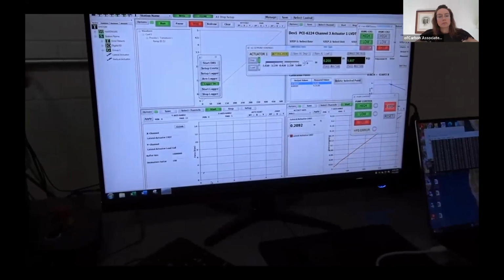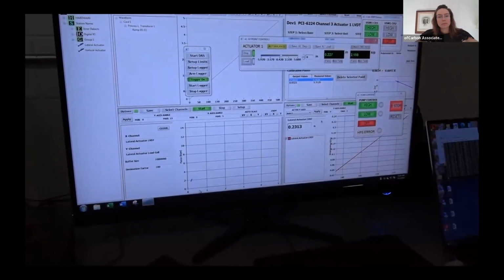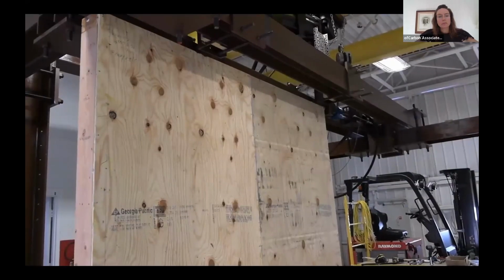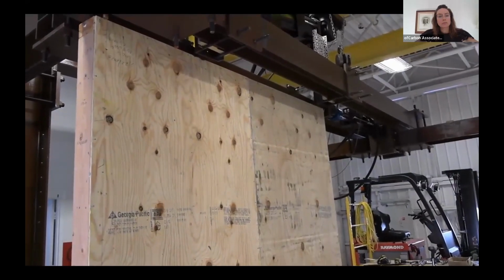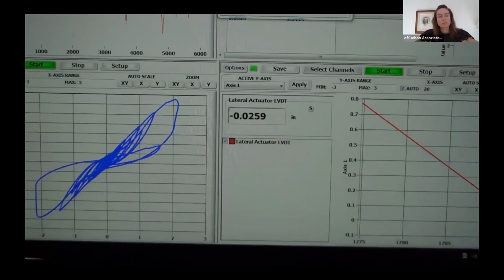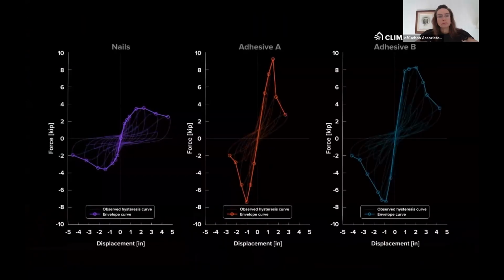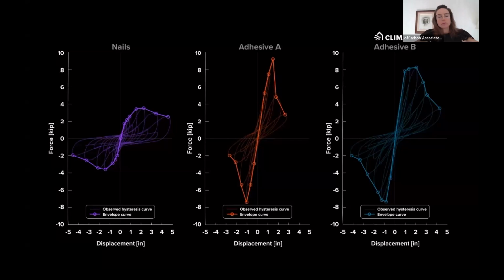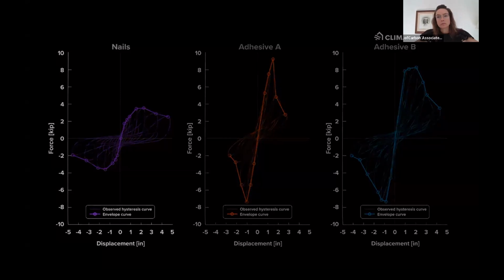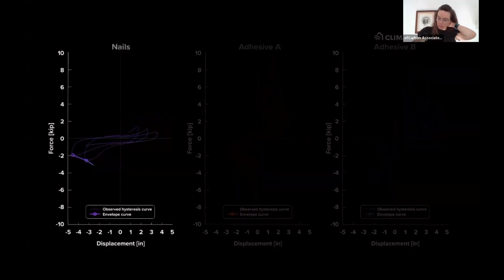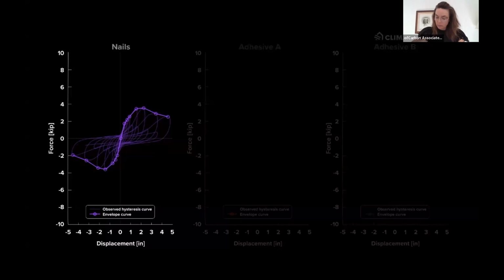But the story is about more than strength. The ability to absorb energy, to displace it, is critical to a wall surviving the dynamic forces of a hurricane or seismic event. The 3 2x4 walls were also measured for their displacement properties. These hysteresis curves show the lag between the force applied and the wall's response to it. The greater the lag, the better the system's ability to displace force. For the nails-only wall, the loops remain relatively close to the horizontal axis. This is due to nail slippage as force is applied, known as pinching.